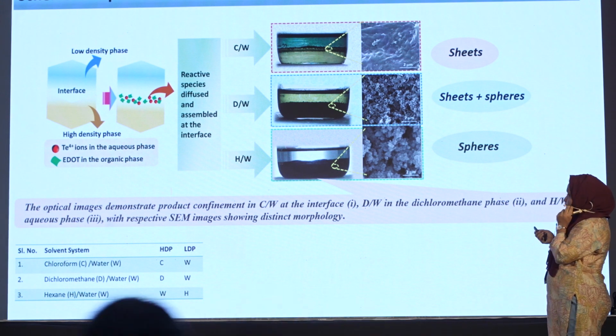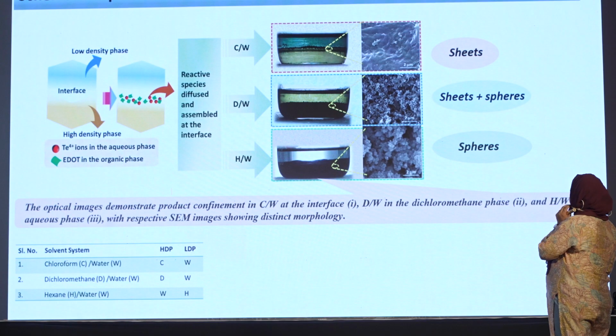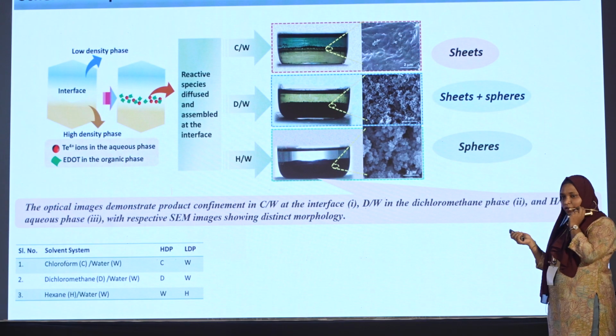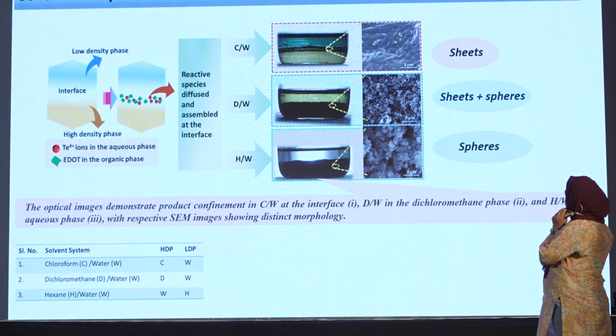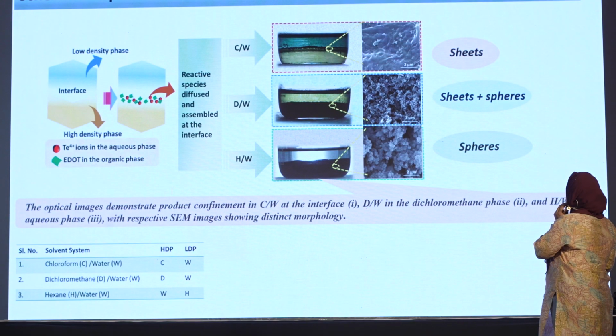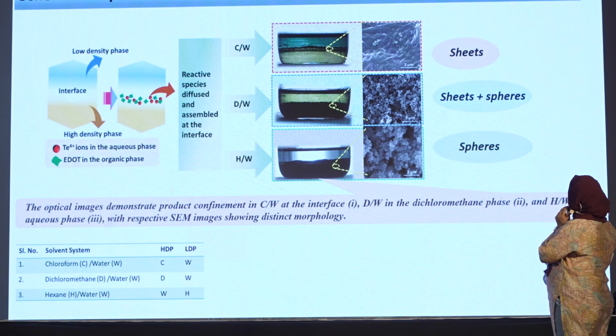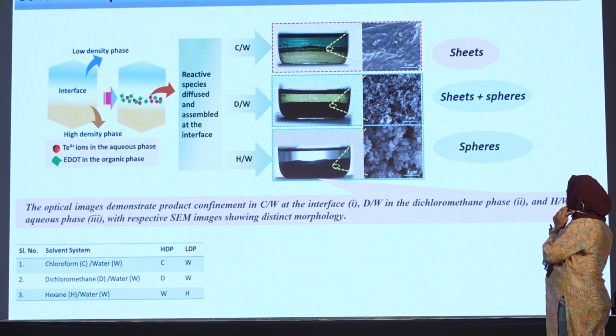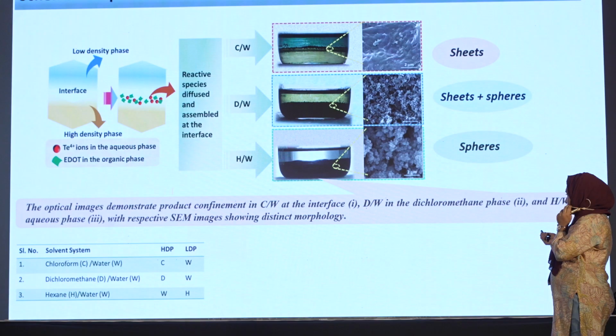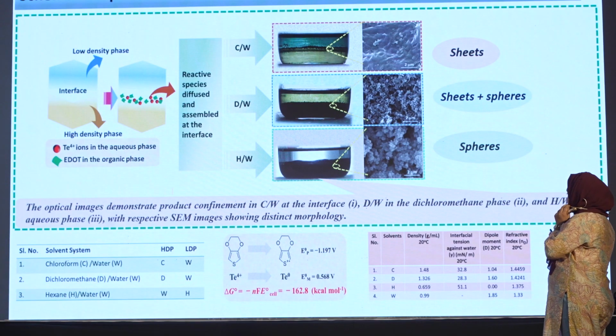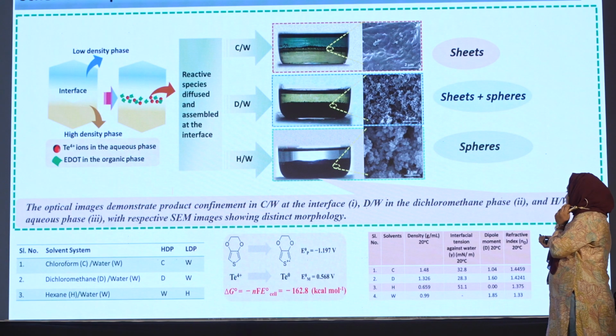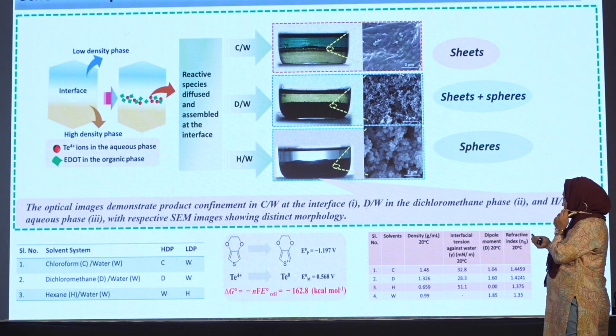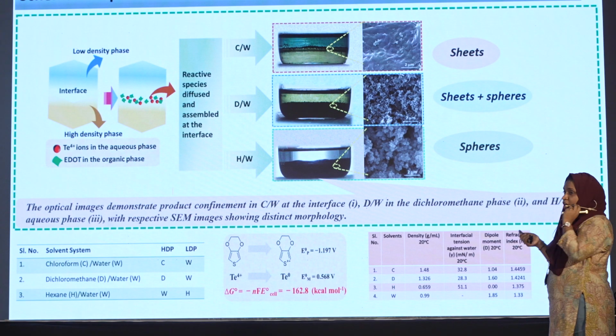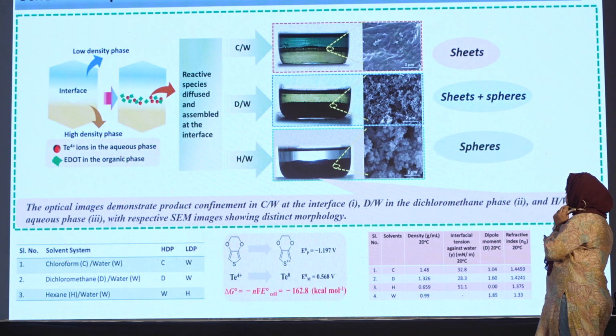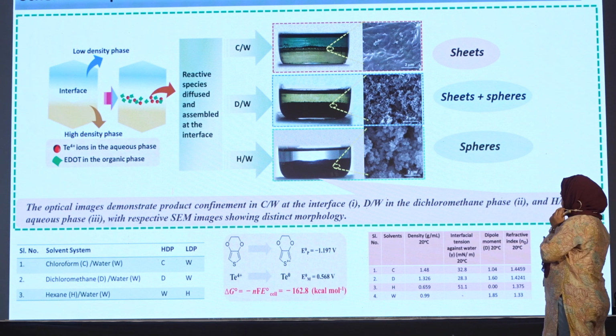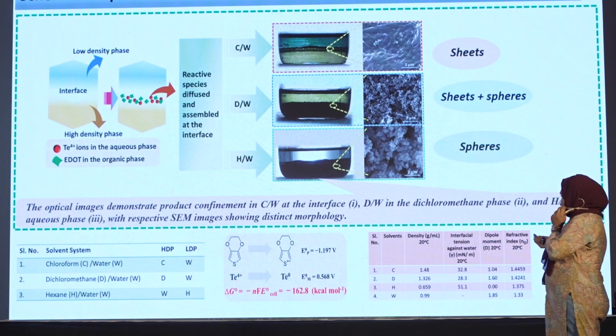Interestingly, when we took the SEM analysis, we found diverse morphology for the same composite. For the chloroform-water system, it is sheets. For DCM, it is sheets and spheres. And for the hexane-water system, it is solely spheres. The synthesis design was inspired by the spontaneity of the Gibbs free energy of reaction for the redox couple involving conversion of tellurium 4+ to Te0 and E-DOT to E-DOT radical cation.